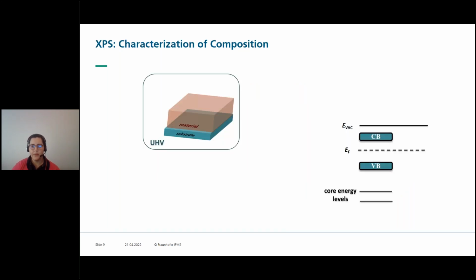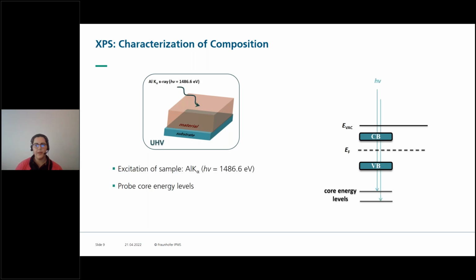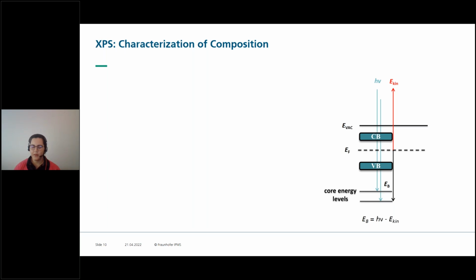So let's continue now with the basics of XPS. On the right-hand side, we have a simplified energy level diagram like we saw earlier, and on the left-hand side, a sketch of a material, let's say, deposited on a substrate. And XPS is commonly performed under ultra-high vacuum. So we have excitation of our sample, for example, using an Aluminium Kα X-ray source with about 1500 electron volt in energy. We probe our core energy levels. We have photoelectrons emitted with our kinetic energy. Like I said before, the binding energy can be back calculated.